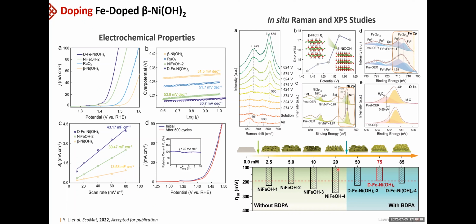Without the BDPA precursor forming reagent, we couldn't use too much iron doping. Actually, we are forming nanoparticles. But with this, we can actually increase the doping amount to the maximum, and that shows very good OER performance. So this is one of the studies we did for the doping effect.